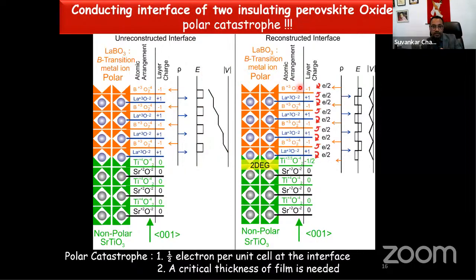Now, to get rid of this diverging potential, one may send half an electron from the top of this thin film to the interface, and your electric field now looks like a zigzag-like electric field, and the corresponding potential is no more divergent; it becomes a convergent potential. So what are the checks of this kind of polar catastrophe scenario? Number one, you need a critical thickness for the thin film. Number two, half an electron per unit cell should be doped at the interface.